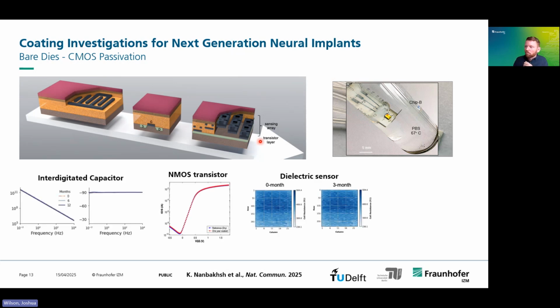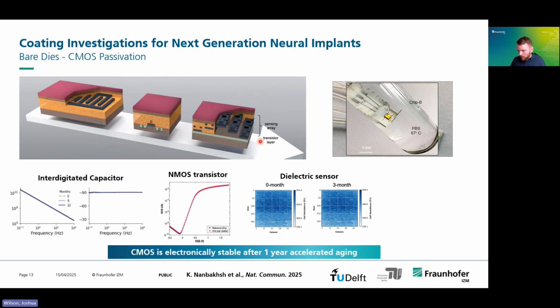And what we see is everything is stable for a year. So what this tells us unexpectedly is that actually the CMOS is electrically stable for a year after accelerated aging. You don't need to do much at all.